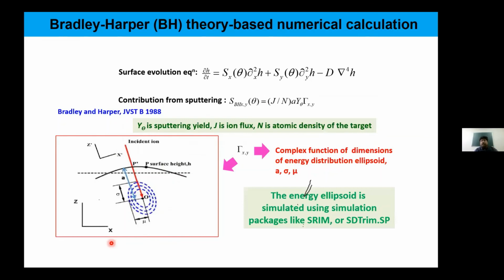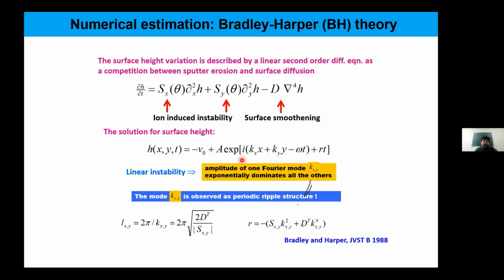And here a complex mathematical function gamma xy needs to be considered, which is a complex function of dimensions of the energy distribution ellipsoid, like A, sigma, mu, etc. And there will be a recoil term also, which is delta. So we can see that the surface height variation can be described by a linear second order differential equation, which takes care of this competition between sputter erosion and surface diffusion.